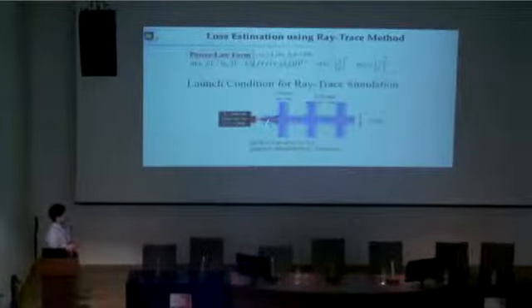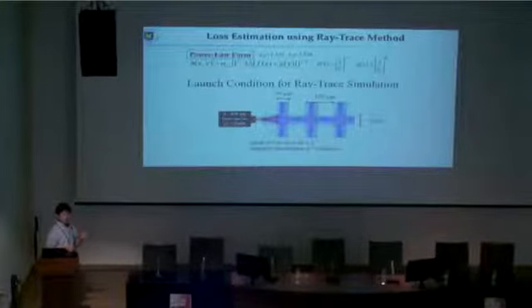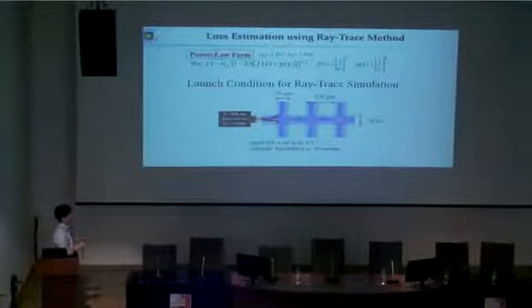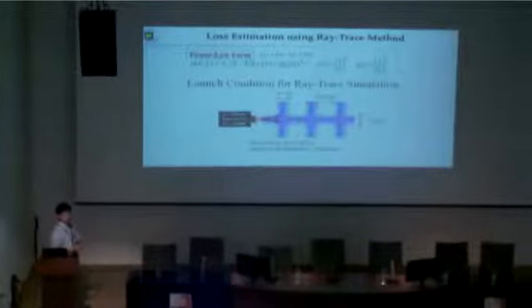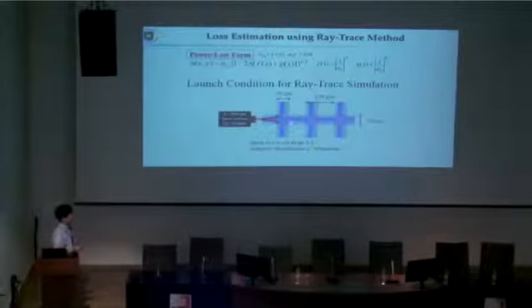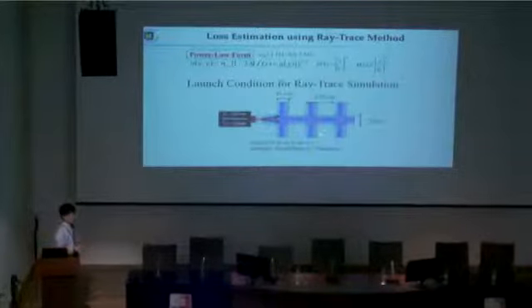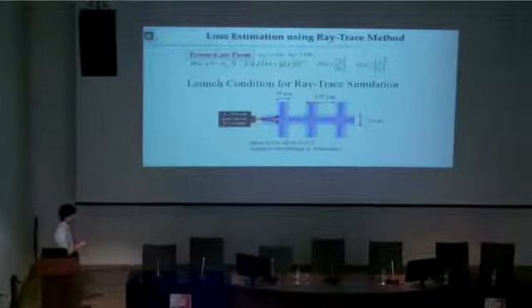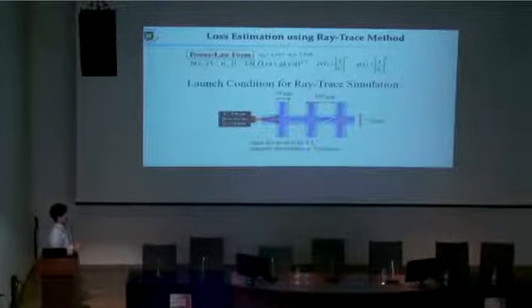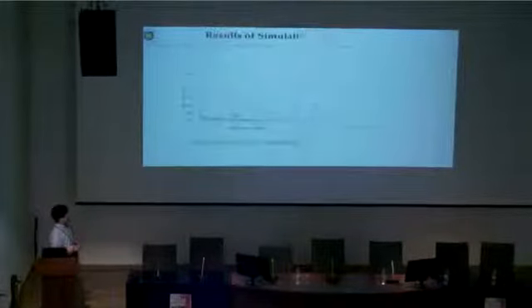This means that at the cross-section, it is very difficult to form the graded index structure in both directions, from the point of view of the fabrication process. Therefore, for the simulation, we suppose that at the intersection, no graded index structure is formed, but just a flat uniform refractive index is dominating this intersection. That is what we suppose. However, despite the SI core structure at the intersection, the very low loss in the graded index core